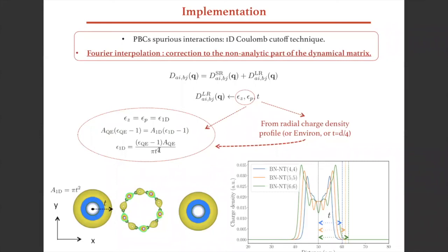However, of course, this is a limit of the model. For example, the ideal way to go would probably be to switch to something similar to what Stengel and Royo have been working on in the 2D framework, and so avoid parameterizing the thickness and get a fully consistent formulation of the problem. But up to now, it's a reasonable choice that we can make easily. It's just, of course, there are limitations related. And actually, for phonons, maybe this is not so important. It could be a bit more important if we want to be quantitative in dealing with electron-phonon coupling. But for phonons, for interpolations at least, it's not a real limit. Okay, thank you.